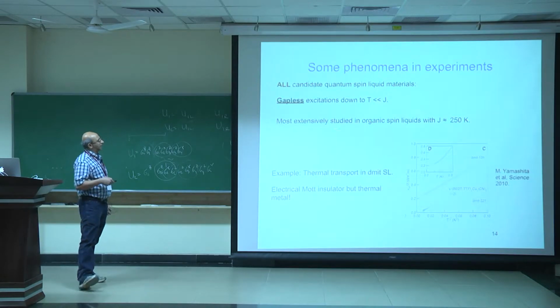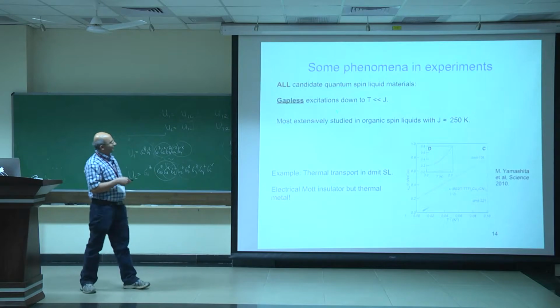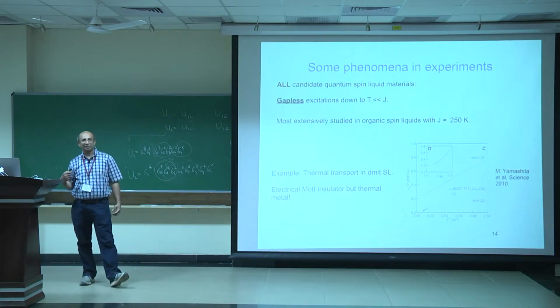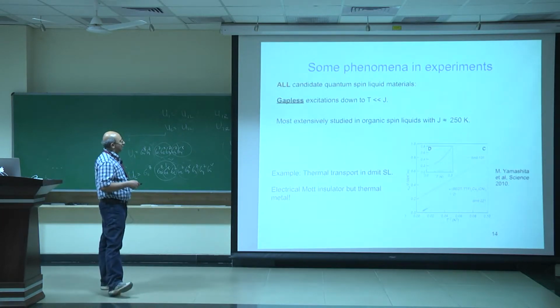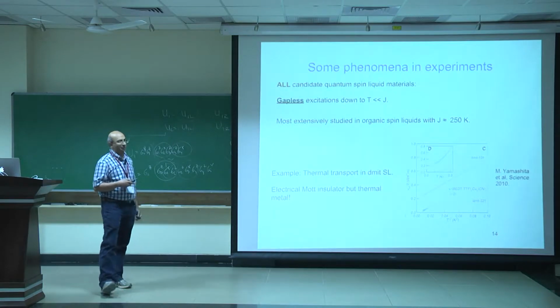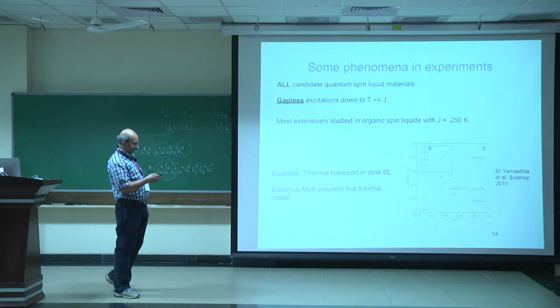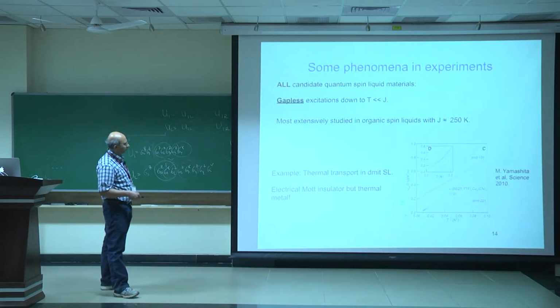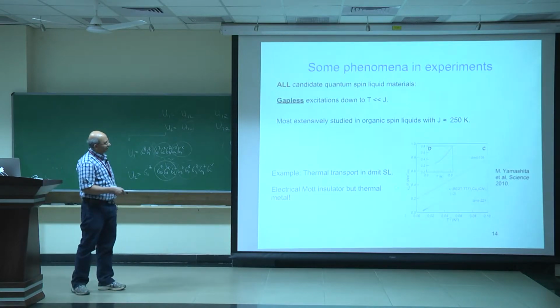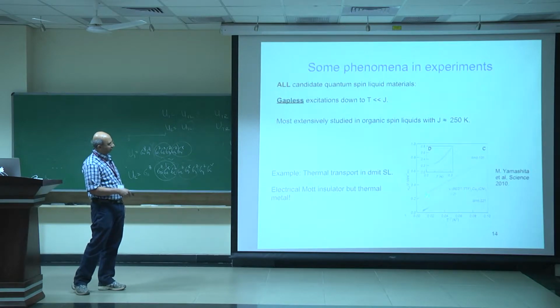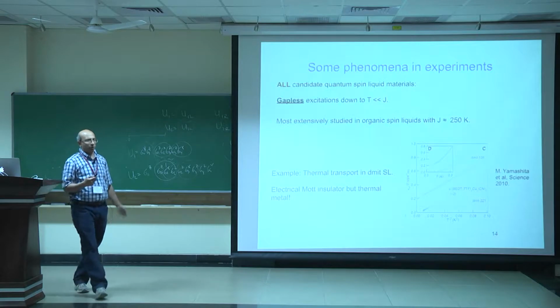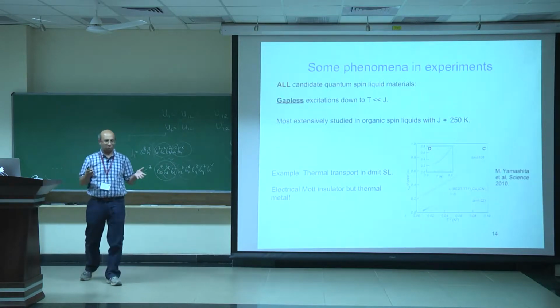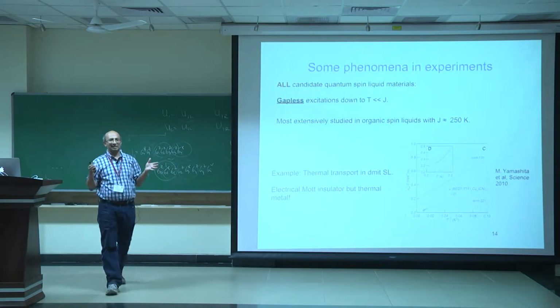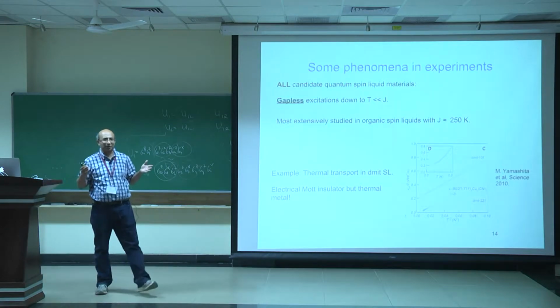So all the candidate spin liquid materials so far empirically seem to have gapless excitations, at least at temperatures well below J. We, of course, never know whether it's a strictly zero temperature property or not. And this has been most extensively studied in these organic spin liquids with J on the order of 250 Kelvin, and they seem to be gapless down to at least 200 millikelvin. As an example, in this DMIT material, I already showed this data in my very first talk. Even though it's an electrical insulator, the thermal conductivity divided by temperature extrapolates to a constant at zero temperature. So it conducts heat like a metal, even though it conducts electricity like an insulator, right? So what this means is that this organic material, which is very close to the Mott transition, has managed to retain some aspects of the metal, at least as far as heat transport is concerned, even though as far as electrical transport is concerned, it's an insulator.